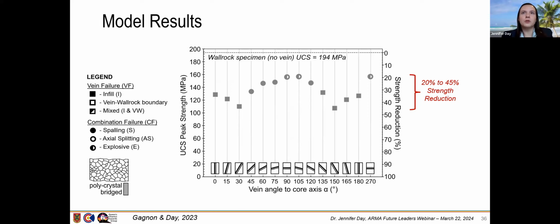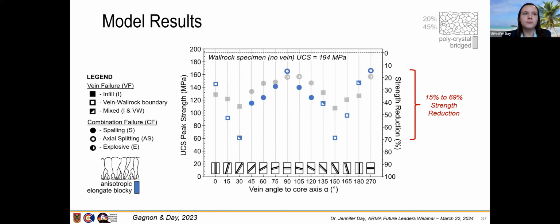In the polycrystal bridged type of vein microstructure, there is a 20 to 45% strength reduction from the wall rock only specimen with no vein. In the anisotropic elongate blocky, there was a 15 to 69% strength reduction. In the other 2 cases, which are available in the paper, there was even more strength reduction observed, but I'll leave that for you to go find afterwards.